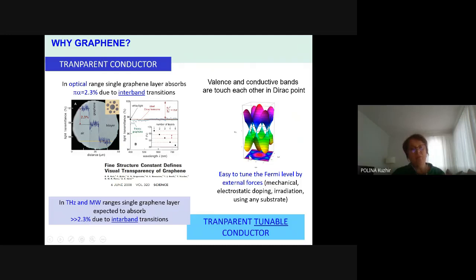So it means that any external force, like small mechanical deformation, even just when you put your graphene onto some substrate, or electrostatic doping, or illuminating graphene with optical or some other radiation, will give a substantial change in the position of the Fermi level, which means you could have either an almost insulating material or a material with very high conductivity. So again, why graphene? It is highly absorptive and it is highly tunable.